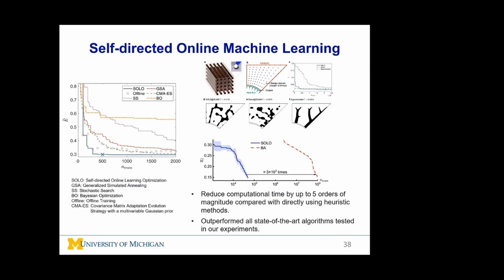Here are some examples to demonstrate the power of this approach. We have found that it outperformed all state-of-the-art approaches, and it accelerates the calculation by up to 5 orders of magnitude. This allows us to solve many problems not possible before. For instance, we can use this approach to optimize the shape of the electrode to improve battery performance.